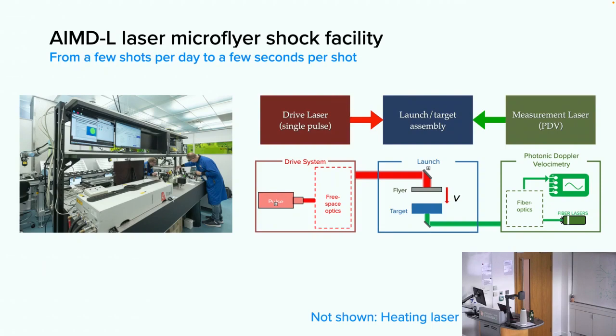It has two key components. It has a drive laser, which is going to drive a flyer, like in the schematic that I showed a second ago. And it has a measurement laser, which is going to measure the velocity of the back surface of the target. I neglected to mention this in the previous slide, it's looking at that back surface and how it's moving in response to the waves that reach it, which is our primary diagnostic in this kind of test.